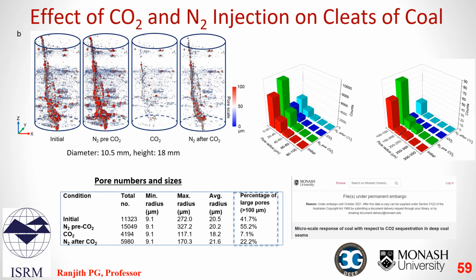We also conducted pore network modeling to quantify the pore geometry. We found some large pores here in red color mainly contribute to the connectivity and control the permeability changes for the fracture network. Pore scale imaging and modeling techniques help us to understand the underground flow processes and design effective gas storage and resource recovery.